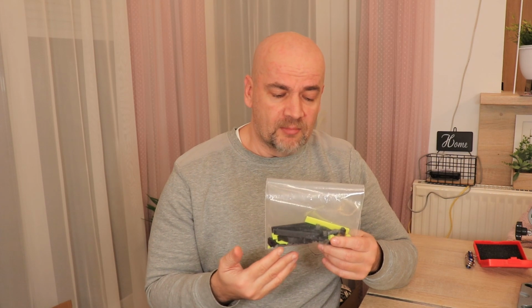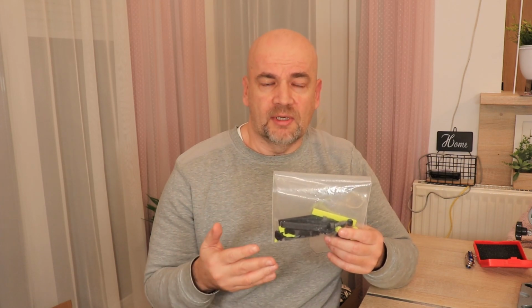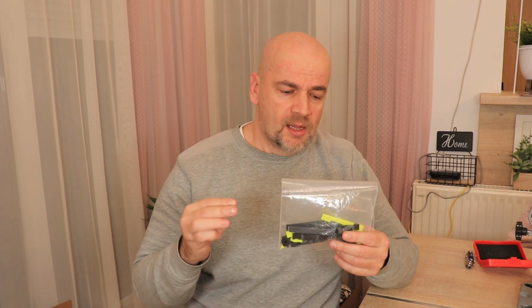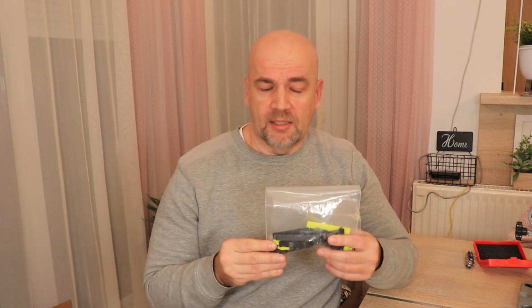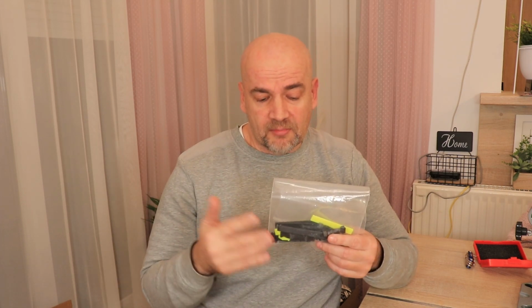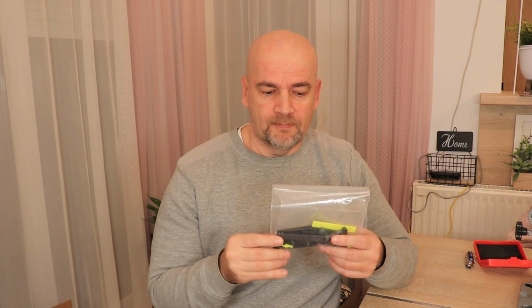And now the conclusions. Well, you saw the numbers for the first three filaments, the PLA, META and PLA plus. They're very similar materials. It is very nice that META can be printed at lower temperatures. This may be important for somebody with those cheaper printers, which are not able to print at higher temperatures. But still, from these three, I think the PLA plus is my favorite, especially because of that impact test. So it's a tougher material.